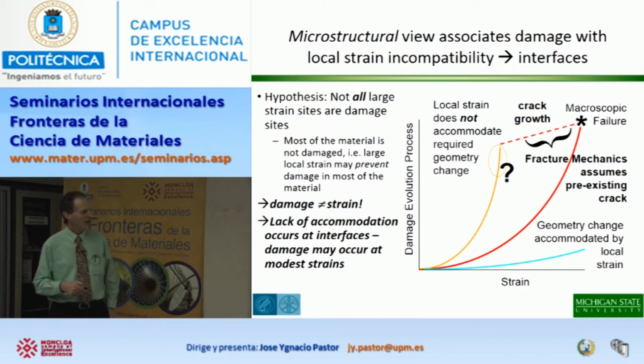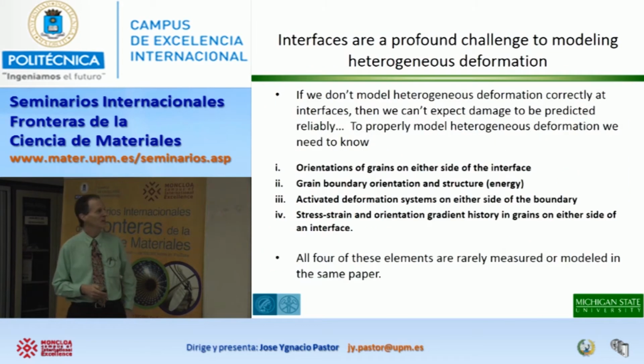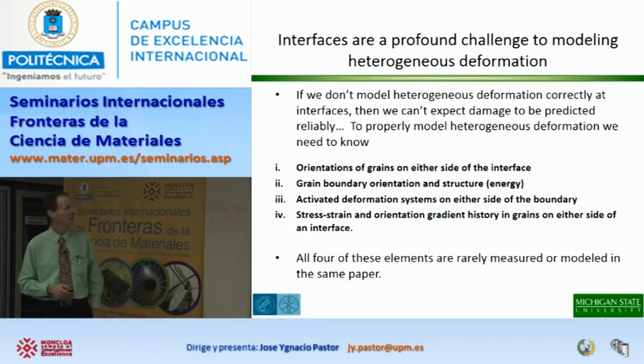So what happens here is really our motivating question: how does this crack come about? The main point I want to make is that damage is not the same thing as strain, and that the lack of accommodation typically occurs at interfaces. And that may actually occur at fairly small strains in comparison to other regions. So basically, if we don't model the heterogeneous deformation correctly at an interface, then we cannot expect damage to be predicted reliably.